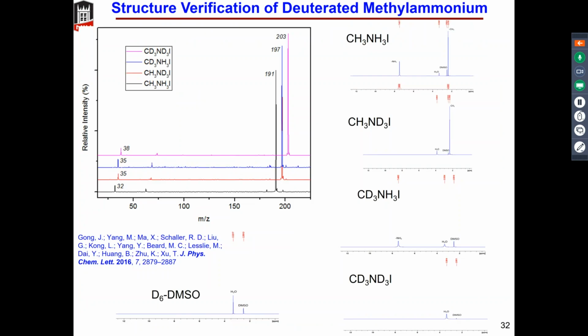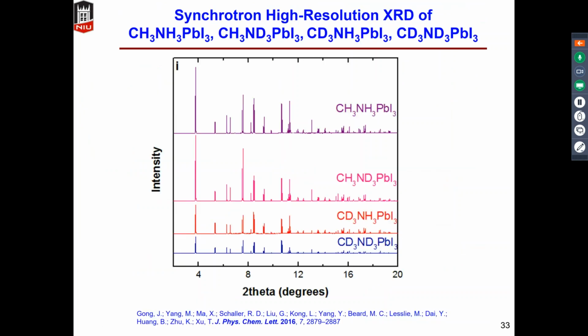We also carefully examined all the intermediates that we used to synthesize these 4 different isotoped MAPbI3, and these are their NMR and mass spectroscopy, and we found that they are exactly what we expected. So now we are confident that we can compare these single crystals in terms of their optoelectronic properties. We also conducted synchrotron high resolution XRD of all the 4 single crystals, and found that these single crystals are all comparable with each other. So whatever we study based on those single crystals should represent the